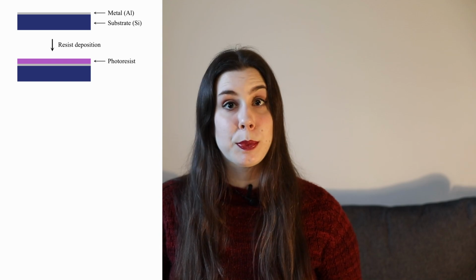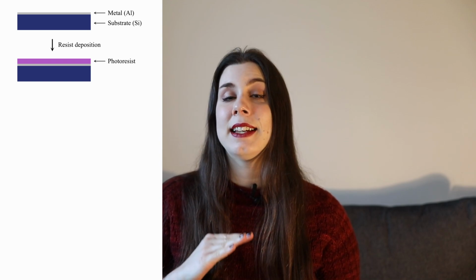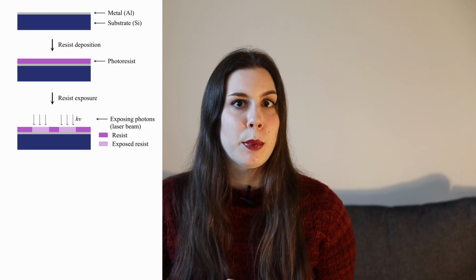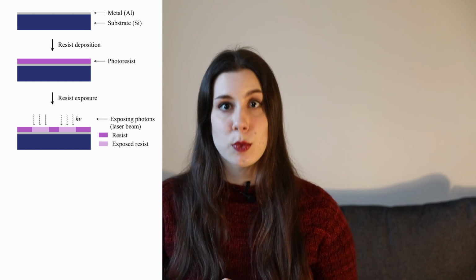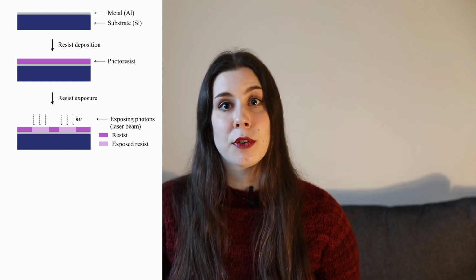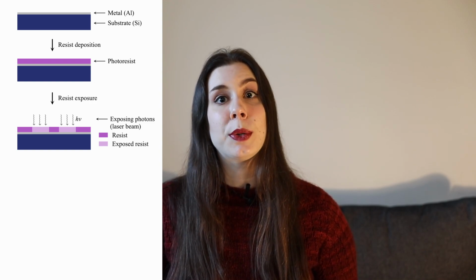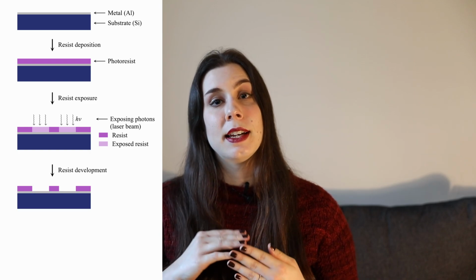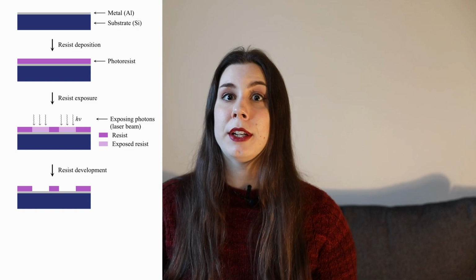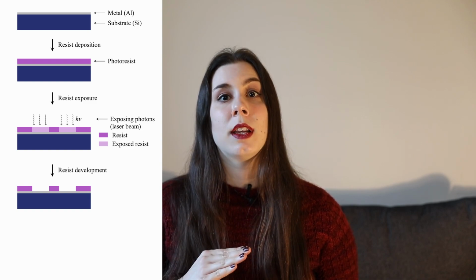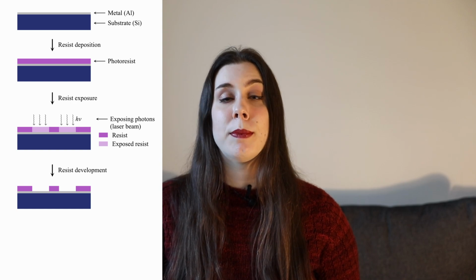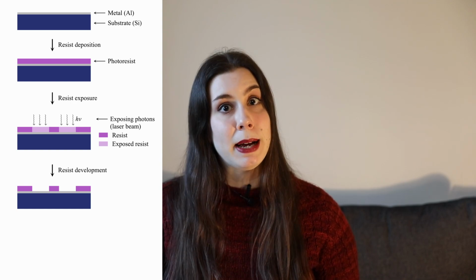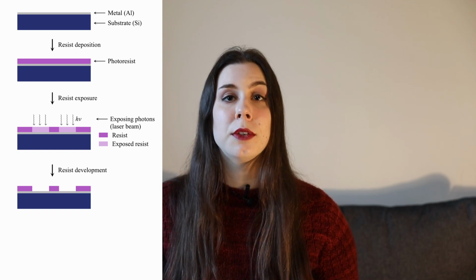The way we're going to do this is we're going to first deposit a layer of photoresist on top of our aluminium film. A photoresist is a polymer that's sensitive to certain wavelengths of light. And what we can do is we can take a layer of this photoresist and selectively expose certain areas of it, for example, where we would like to have the gaps of our qubit capacitors, to light of this wavelength. This will chemically change the exposed areas of the resist, which in our case will make them soluble in a liquid we call photodeveloper. And if we then take this selectively exposed resist and submerge it in a beaker of this developer, the exposed areas will be dissolved, while the unexposed areas of the resist will remain behind on the wafer. And this way we can create a pattern in the photoresist layer on top of our still continuous aluminium.